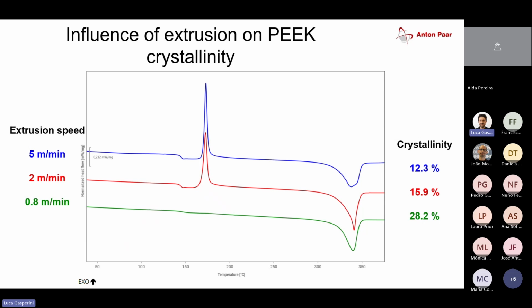And in the last one, the last application that Florian was showing was an extrusion, and with different extrusion speeds. So we also performed an experiment. In this case, this was an extrusion of PEEK, polyether ether ketone. And we wanted to see how much the extrusion speed affects the crystallinity of the final product. So we had 3 different extrusion speeds. The highest one was 5 meters per minute, the mid one was 2 meters per minute, and the third one was less than 1 meter per minute.